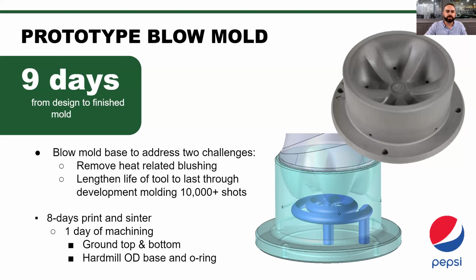So we got into Pepsi's R&D lab over in New York, where they were having issues with the bottom of their, well, this isn't the best representation, but the bottom of their blow mold bottle. What they found was it was more of a heat transfer issue. So what we did was, you can see on the top right, that's actually the printed block. All we had to do was basically touch up the OD, and